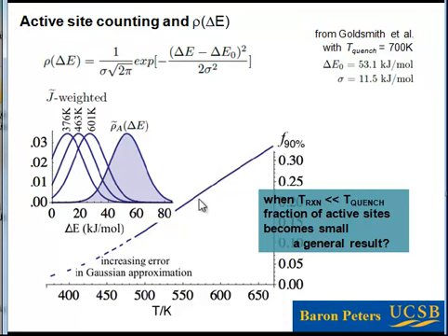So I think what we should expect is that, if the site was made at high temperature, it has a long tail of different structures. A long tail of different structures probably means also a long tail of different reactivities. And a long tail of different reactivities means that you should see this declining fraction of sites contributing to your reaction rate as a function of the temperature on operation. And so, I think that there are some kinds of predictions that we're beginning to be able to make.